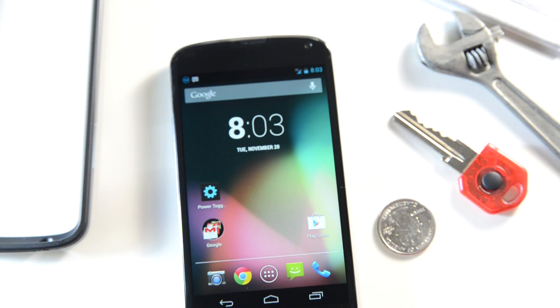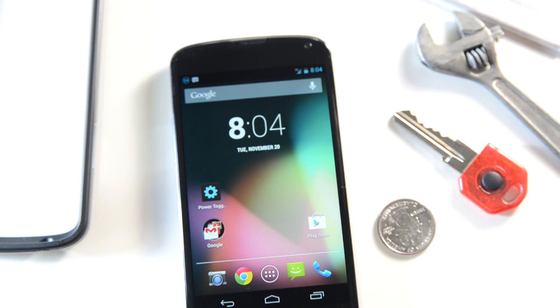What can scratch it is something like quartz, which is sand — tiny little grains of sand. That's supposed to be at about 1,000 on the Vickers scale, so that's harder than this glass. I can see sand scraping up against this giving it little fine scratches. Diamonds, of course — diamonds are up towards 10,000. That's why they use diamond to cut glass. So don't worry about your keys and coins. Worry more about the little grains of sand collected in your pockets.